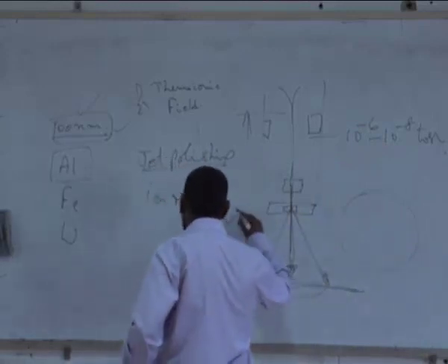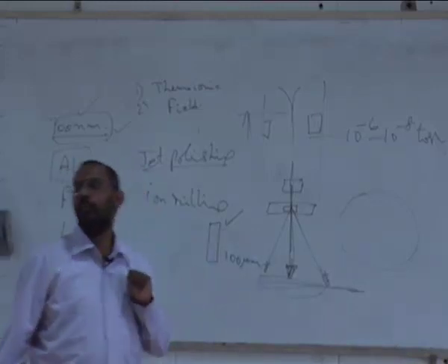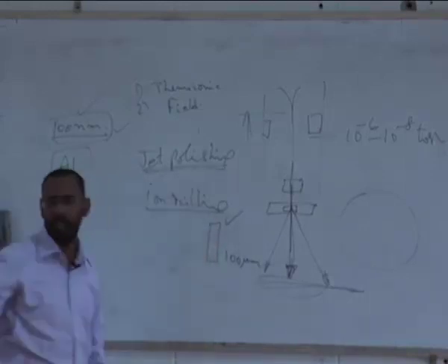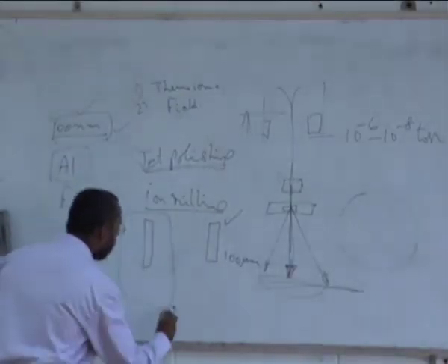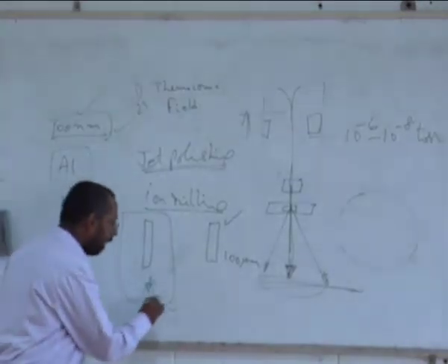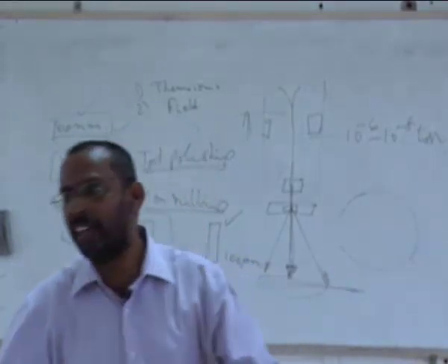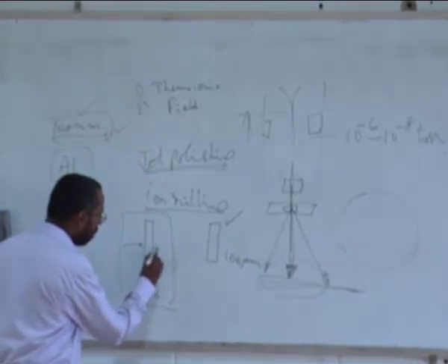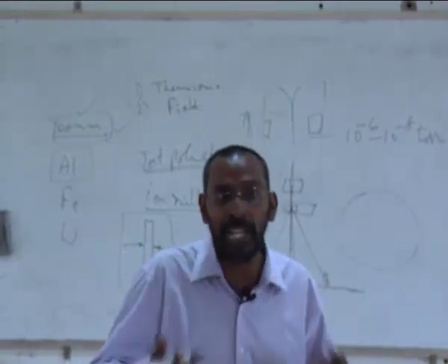So once you make a thin slice like this, similar to your metallic sample, that is when the whole story starts, and you do not use jet polishing, but you use what is called ion milling. What we do is we keep this thin sample into a chamber, evacuate and fill it with argon, ionize this argon gas and allow these ions to fall on the sample like a beam from both the directions. And we call this ion milling because you are milling.